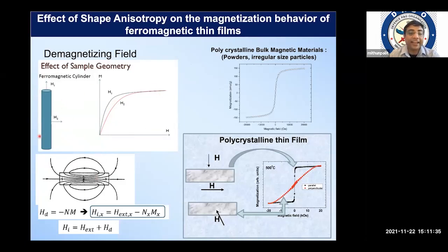If you see a very long rod, the demagnetizing effect is very minimal. If I measure the magnetization along this H1 direction and H2 direction, the plot shows there is not much difference. Of course, there is a difference due to slight demagnetization. However, if I go to a thin film and I measure in this direction and that direction, you see how much difference I realize in the loop. So that is the demagnetization effect. That we will have to cater for when we are talking about thin film.